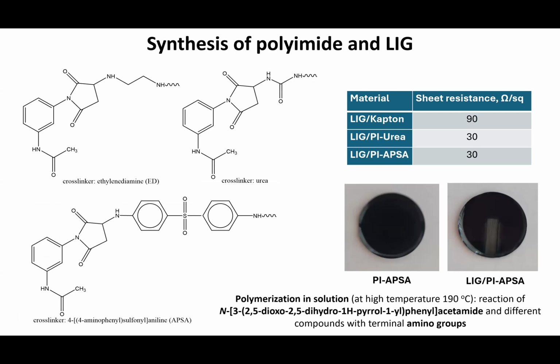And then what we did was take the second precursor, the middle of the 3 steps, and attach 3 different crosslinkers to the end. One is ethylenediamine, or ED, shown here in the top middle. The other is urea. And then at the bottom, you see something called APSA. I'm not going to try to read the chemical formula for that. But they're all slightly different, and they're all polyimides. And we managed to make LIG from all of them.